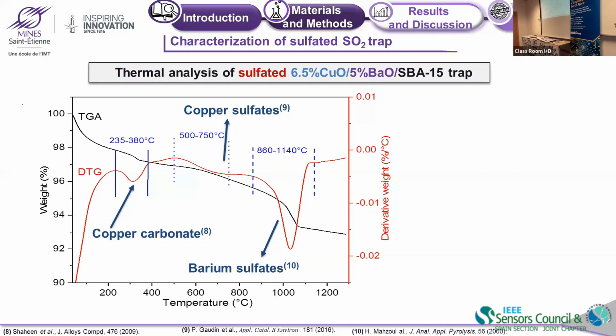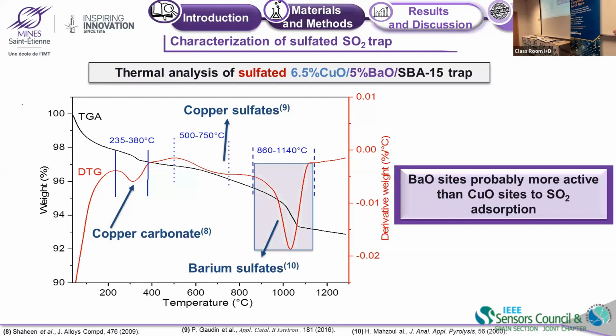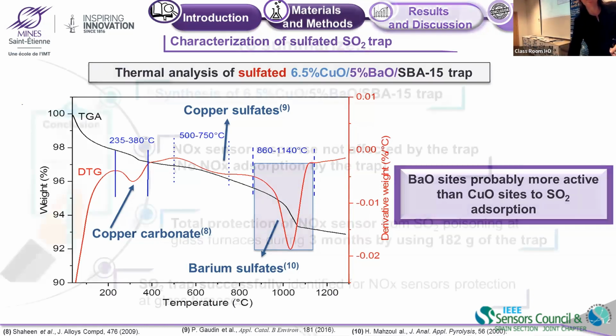We confirm this by thermal analysis of the sulfated trap. Here you can see in black the thermogravimetric analysis, and in red the derivative weight. You can see copper carbonate decomposition here at low temperature, copper sulfates between 500 and 750, and at high temperature we can see barium sulfates decomposition. So barium oxide sites are probably more active than copper oxide for SO2 adsorption, as we can see.